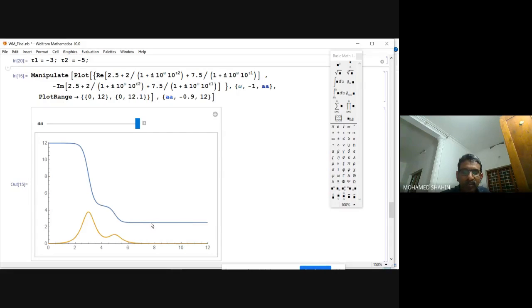If there is no electronic and atomic contribution, then it would be ending at one. That is the dielectric constant of free space. Since there are molecules responding, you will get a higher value. Then the electronic and atomic contribution is here.